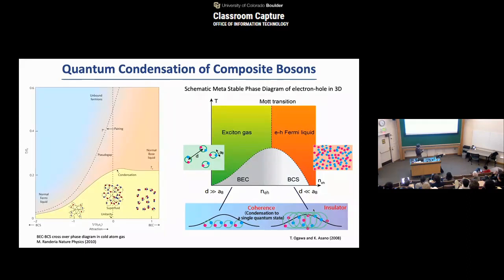Yes. So at finite temperature, you draw this phase boundary. Is that sort of schematic? This is a kind of schematic. So this can be a true phase transition, or it can be a crossover, depending on the system. The idea is that it holds even at finite temperature. In fact, classically that is expected, because if the excitons become dense, the electron and hole that make up an exciton start to see the other electrons and holes. Eventually, at some point, all these electrons and holes will screen each other and unbind the excitons. This is what is expected to happen in the Mott transition.